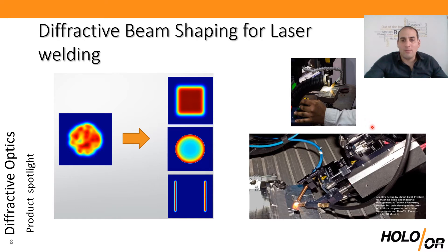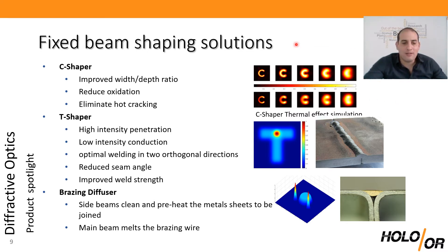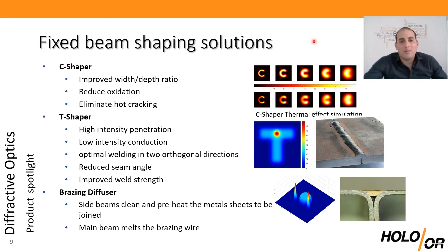You can shape laser spots by multiple approaches. Our approach uses a single component and can fit any laser — you don't have to marry your laser supplier. Holor's fixed beam shaping solutions give you a static shape optimized to your process requirements. The C-shapers have been shown to allow a weld that is better than a ring mode, because the dark area of the C — which has no energy — allows inclusions trapped inside the melt pool to be removed while the beam scans forward. These inclusions pop out like bubbles, increasing weld strength significantly while reducing oxidation and eliminating hot cracking.